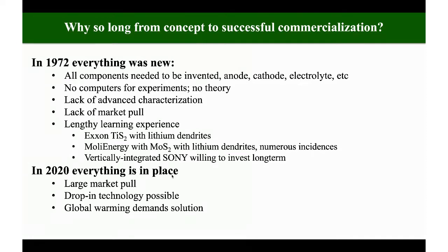There was also a big lack of advanced characterization. So where today you can easily go to a synchrotron and look inside the battery and see what's happening, you couldn't do that then. There was a lack of a market pull. So we had a technology push, but not all that much of a market pull. And there's a lengthy learning experience. So Exxon learned on lithium dendrites. Moly Energy learned some more, and they had numerous instances. So that's why I think there's only one commercially available lithium battery using lithium metal, and that's the Bolloré cars that come out of France, and they use a polyethylene oxide electrolyte and operate about 80 degrees centigrade.